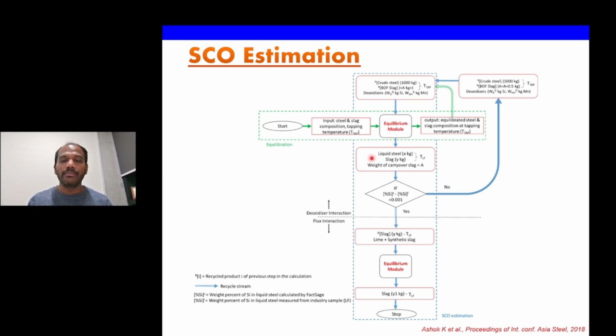If you calculate, basically this will give a liquid steel with x kilogram and the slag with y kilogram at the final temperature, the LF temperature. Initially, the process starts with the tapping temperature, and the equilibrium calculations are subjected to LF temperature, because in the industry I know at the tapping what my composition is, and at the LF what my composition is. Now I have to do the equilibrium calculations with the unknown, and now the process involves in the industry where we collected data. Basically, it is silicon killing in the deoxidation process.